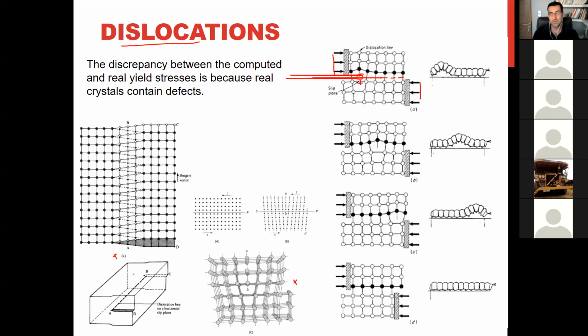And the reason is simple. By just knowing dislocation, we cannot explain. We can explain why we have low stress level for plastic deformation, but we cannot explain it for strain hardening. Okay, we reach that critical shear stress. It means we reach that stress level that can move a dislocation. That is okay, so the plastic deformation starts, but why for further deformation do we need higher stress? What is behind the strain hardening? So to answer this question, we have to know more details about dislocations.